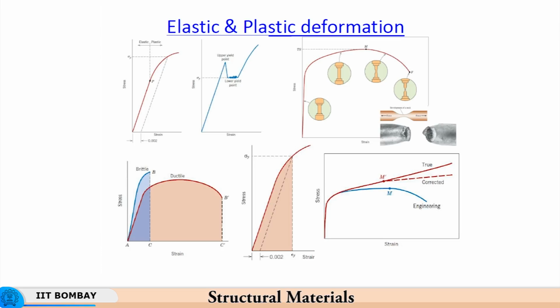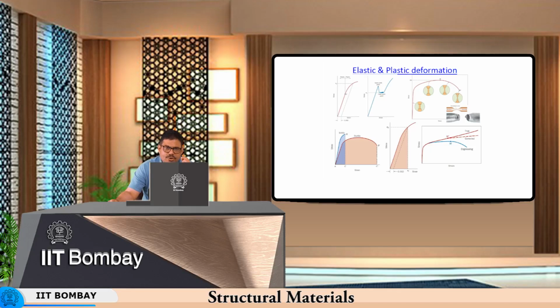So, the strain was distributed absolutely uniformly, but here the strain is non-uniform because the cross section that is unable to support the load first becomes the section where the strain gets concentrated. Strain concentration means more depletion of area, cross sectional area depletes faster, and when it depletes faster, the rate at which the stress rises increases faster, and that is why the load carrying capacity of the cross section drops very rapidly over here, and then you have a fracture which is called a ductile fracture or